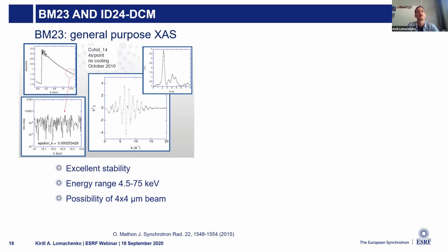Talking a little more in detail about the beamlines: BM23 is a general purpose XAS beamline with excellent stability, broad energy range, and the possibility to use a microbeam down to 4 microns, which is not often used for chemistry - more important for physics - but can be used as well. Main applications in chemistry on this beamline are ex situ and in situ operando studies, but relatively slow chemistry, with a time scale of minutes or tens of minutes, and also industrial experiments.